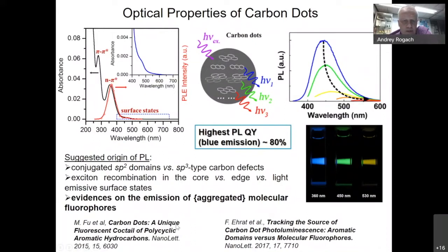And we say here that carbon dots are a unique fluorescent cocktail of polycyclic aromatic hydrocarbons. And these polycyclic aromatic hydrocarbons are nothing else than this kind of molecules, which are shown here inside this schematic picture for carbon dots. So when we excite this cocktail with different excitation wavelengths, we can preferentially excite smaller domains, and then they will emit blue light, or we can move on and excite bigger domains, and they will emit green light, or we can change the excitation wavelength and excite the largest domains inside here, and then these materials will emit orange light. And this has nothing to do with the actual size of the carbon dot. For that reason, we should never call them carbon quantum dots in this way, because what counts here are actually the sizes of these polycyclic aromatic hydrocarbons.